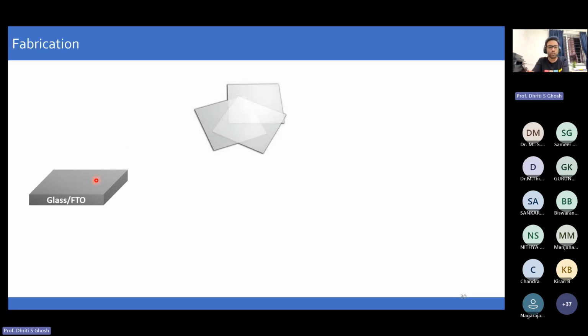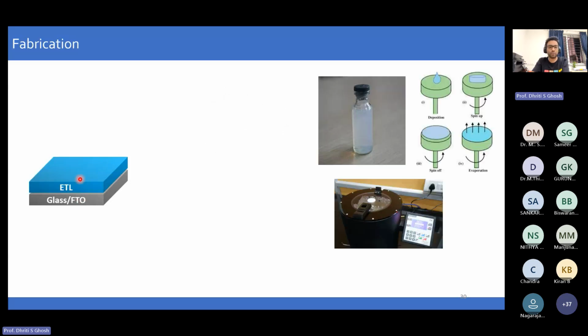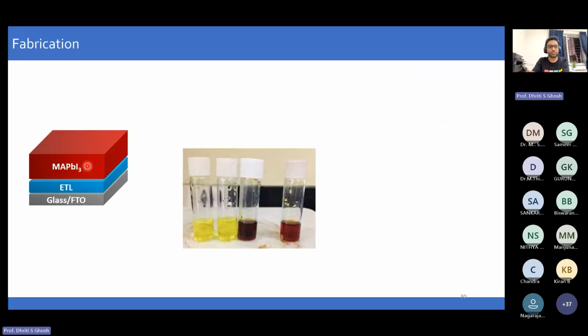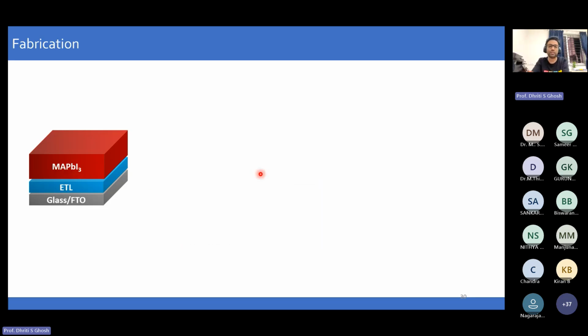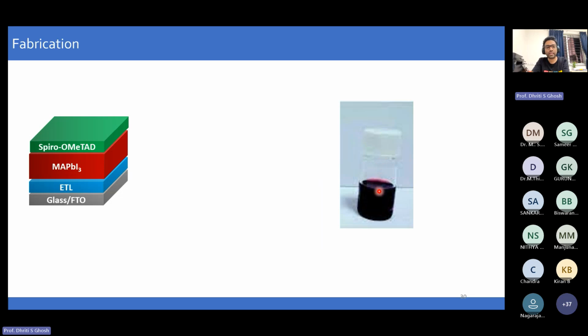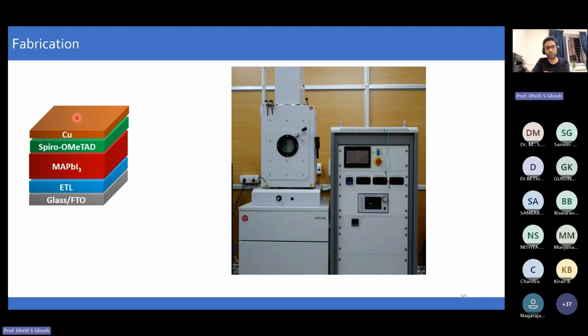Okay. So how do we make it? We take a glass which has FTO coated on it. Then we put the first layer, which is the electron transport layer, by spin coating. This is the spin coater. This is the solution. Then after that, we deposit the perovskite material. In this case, this is MAPbI3. This is ABX3, a different type of perovskite. Again, we use spin coating. After that, we use spiro-OMeTAD, which is an HTL, hole transporting layer. It goes on top of this one. And finally, we use the evaporator to deposit the final electrode.